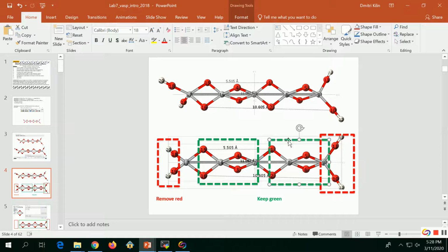If one doesn't do it, it will be like a simulation cell where atoms are jammed close together, which will immediately shrink the gap to zero if it was a dielectric, or expand to a very large value if it was a metal. So it will be very wrong results. Yes? So if I do not put the vacuum over there and then do the minimization? No, it will not fix. You cannot do it. There are special commands to adjust the size of the cell, but they will fix only small corrections. If you start from a predominantly jammed, wrong size of the cell, nothing will help you.